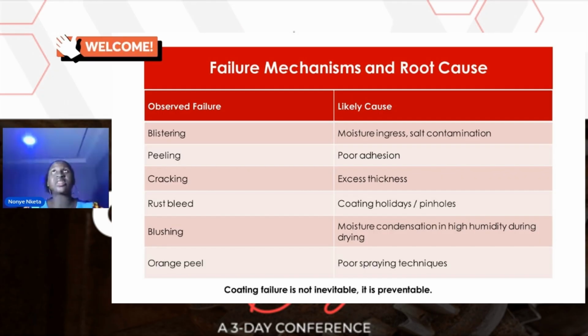You're likely to get the paint to peel. And if you don't get the right surface profile, because surface profile provides the anchor for this product to adhere upon. So if there is no proper surface preparation, you don't have the right primer beneath the top coat, it is likely not to stay. It is actually very common.